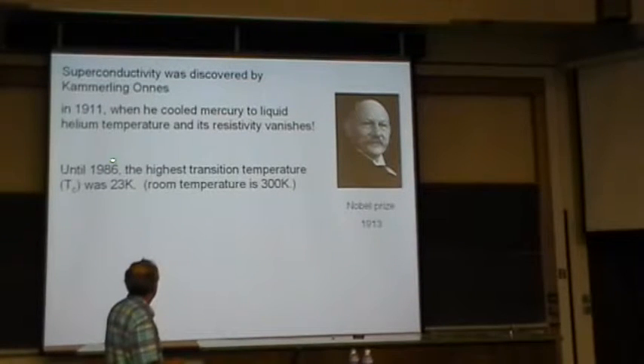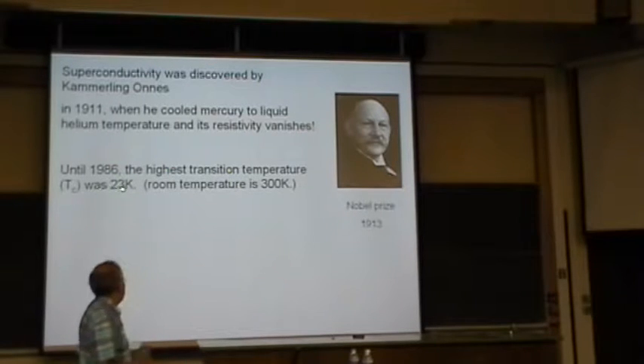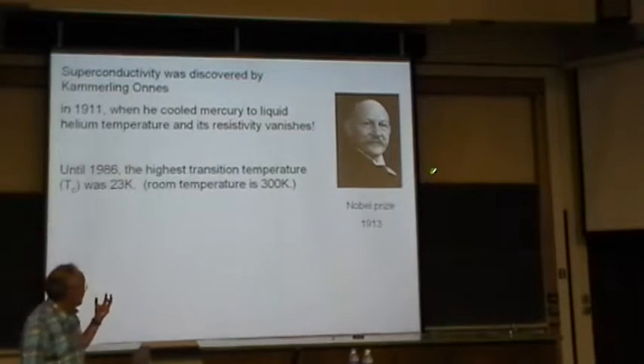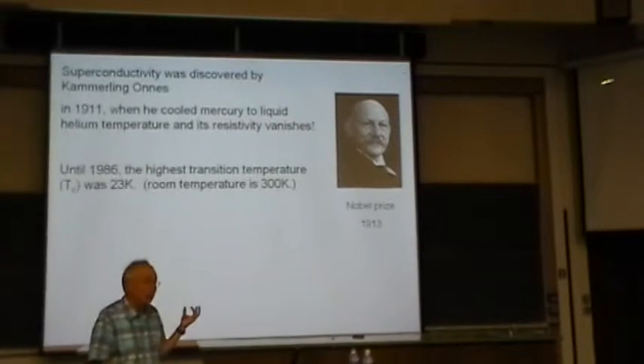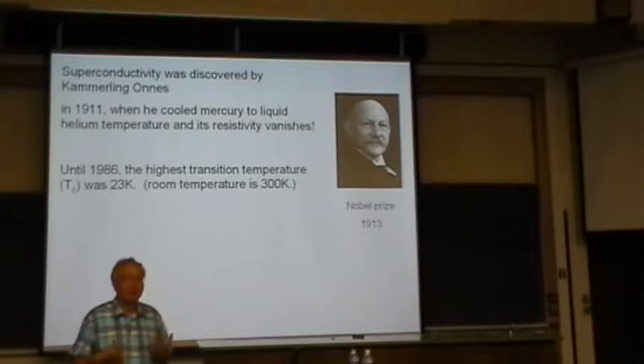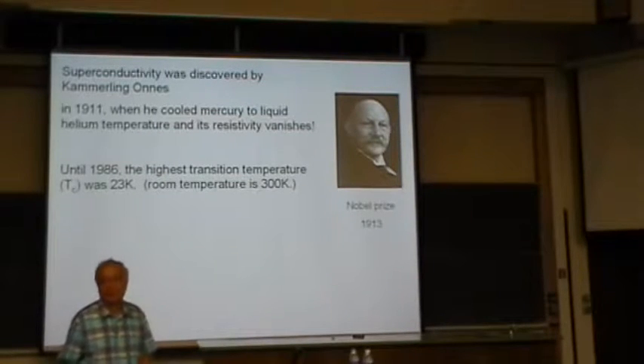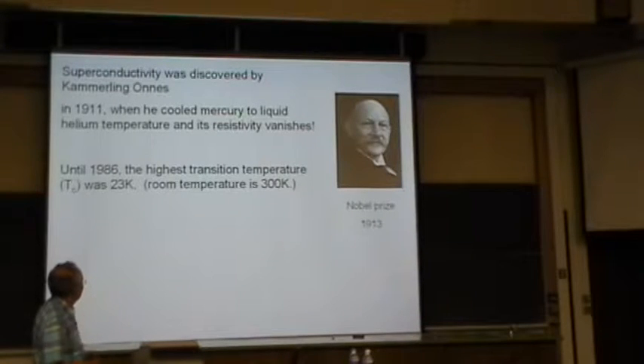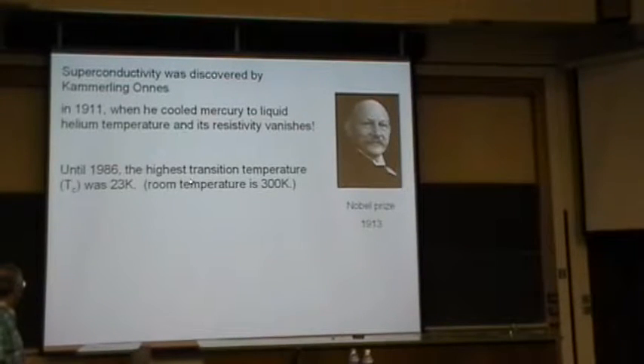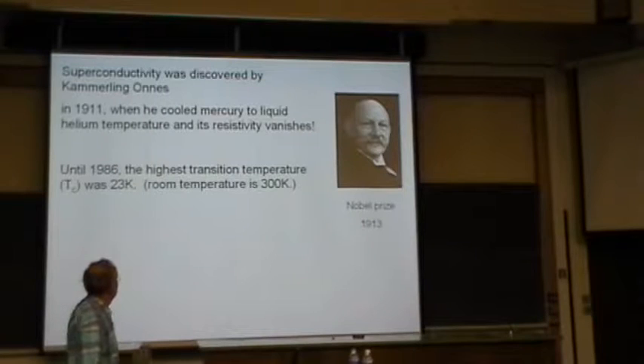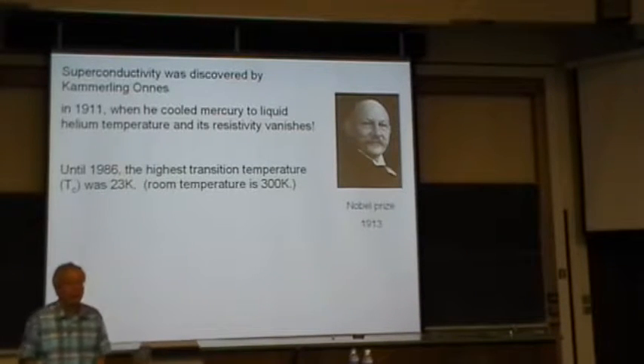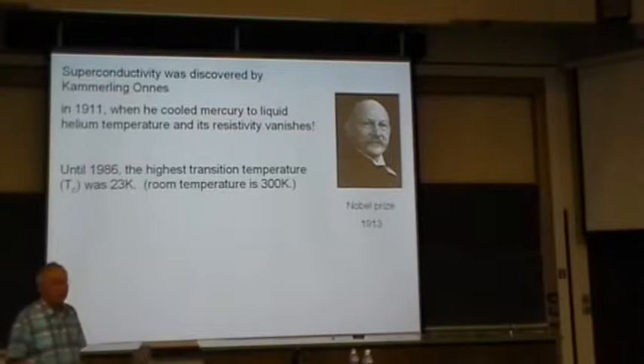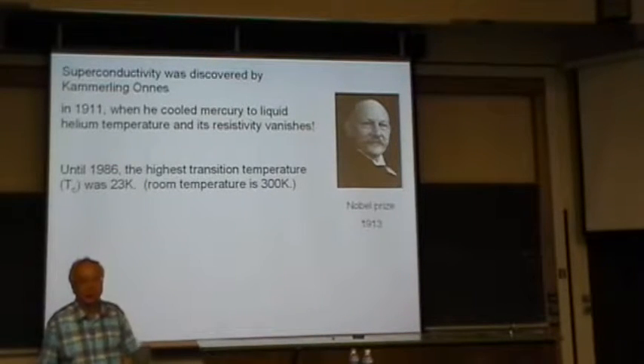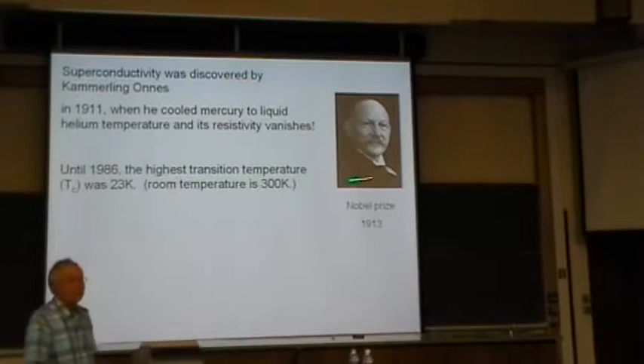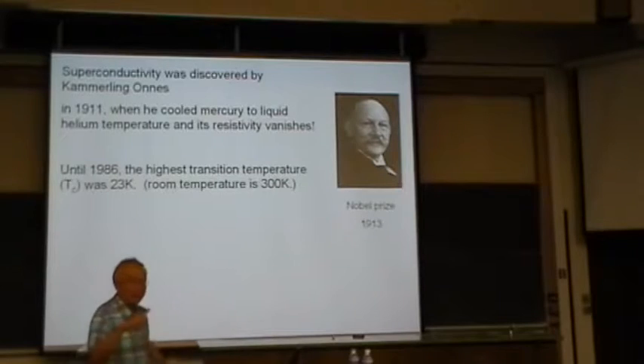Now, for 75 years, the highest transition temperature, so this happens only at low temperature. See, the reason he could do this was that he was the first man in the world that was able to liquefy helium. So he had a monopoly on what we call low temperature physics for a number of years. And for some reason he decided to look at mercury. But until recently, the highest temperature at which you can achieve this is 23 Kelvin. Just to calibrate, room temperature in this Kelvin scale is 300 degrees. And the lowest you can get is 0 Kelvin. Right? So this is less than 10% of the way to room temperature. So it's very, very cold.